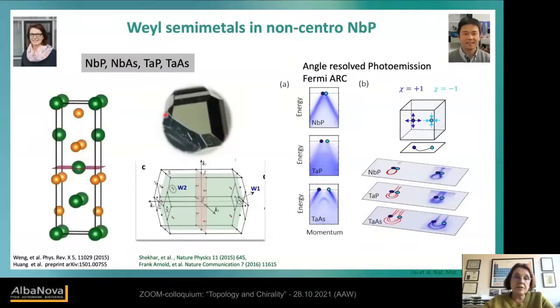So the first material, which was predicted by Andre Bernevig's group and probably Hasan's group at the same time, was simply also a success because there were predictions before, but this material was easy to grow. It's a very simple crystal structure. It's a non-centrosymmetric compound. If you do a calculation in reciprocal space, you find many Weyl points which are quite close together, which is quite often. So in non-magnetic materials, these Weyl points are very close together. In magnetic materials, they are a little bit farther away.